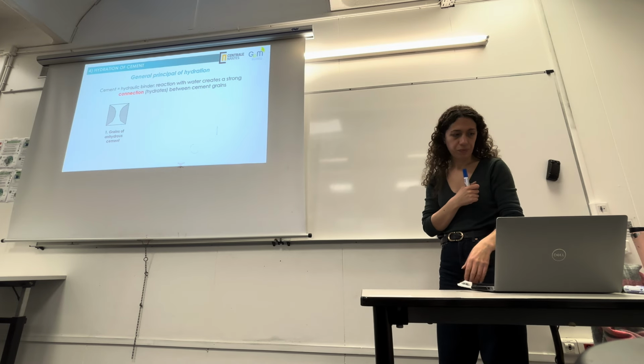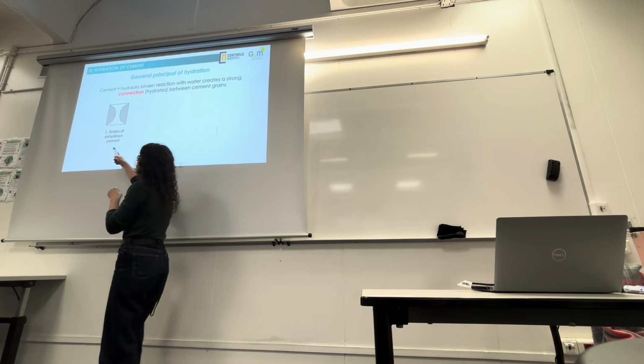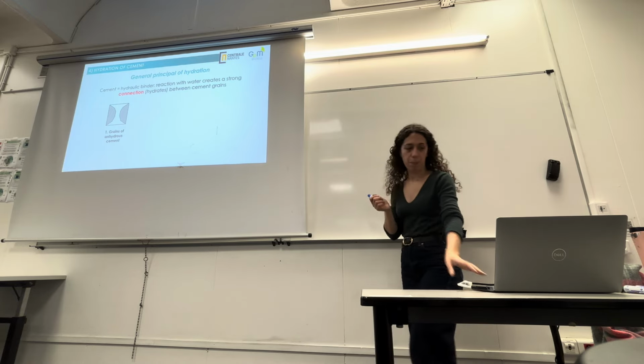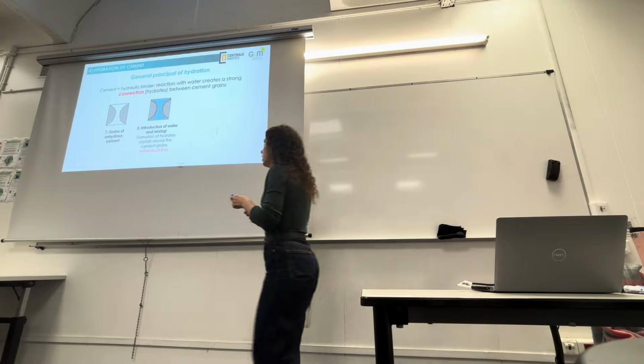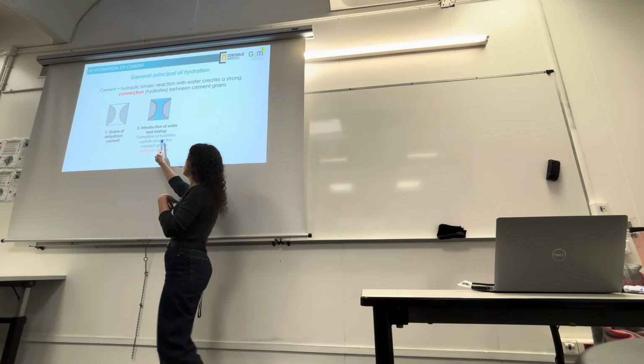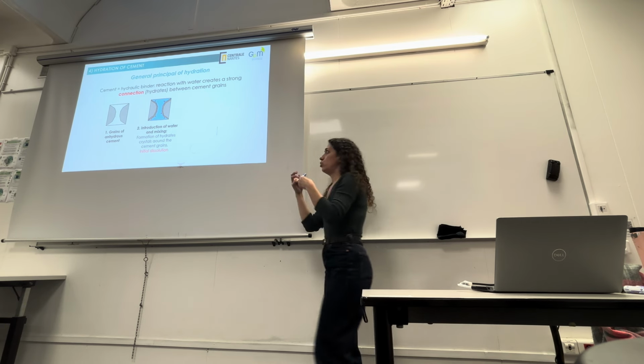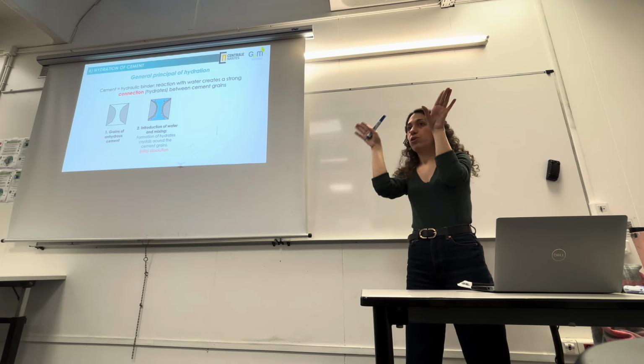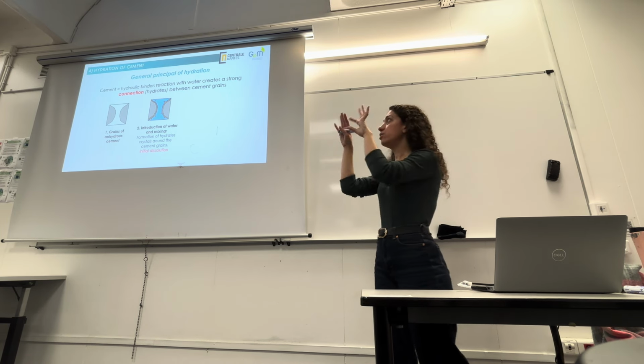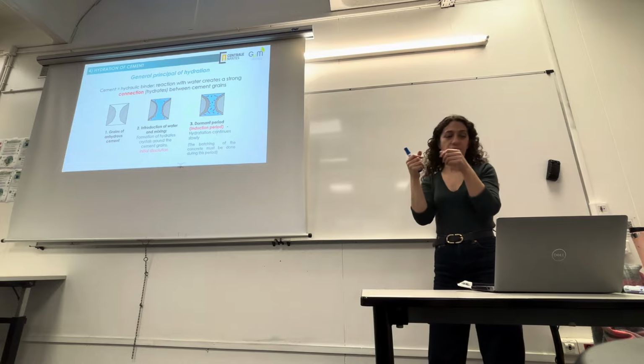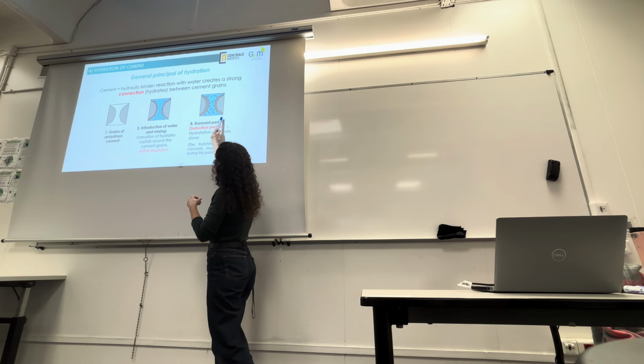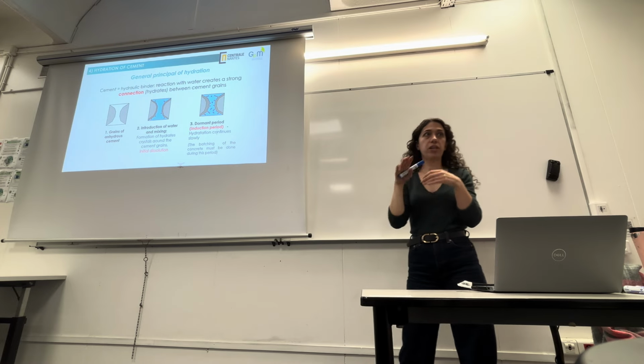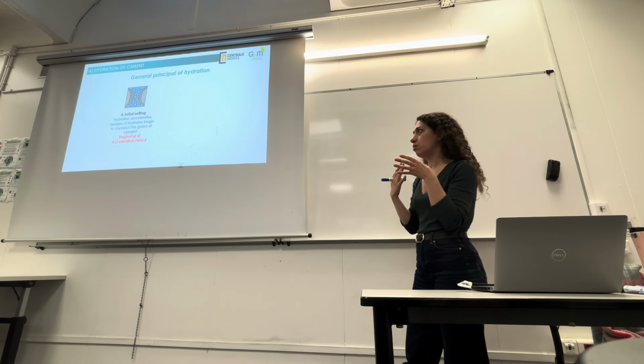First, in your anhydrous cement, you have your grains of anhydrous cement. They are dry, they are just grains of cement. And then you get in contact with water. You mix. You have the formation of hydrates, which crystallize around the cement grains. This is the initial dissolution. You dissolve your cement grains, and the hydrates in contact with water will precipitate at the surface of the grain. And during the dormant period, the induction period, the hydration continues slowly. The placing of the concrete must be done during this period. You still have the dissolution of the grain of anhydrous cement, but you can see that more and more hydrates protect the cement from water. That's why the hydration is slower.